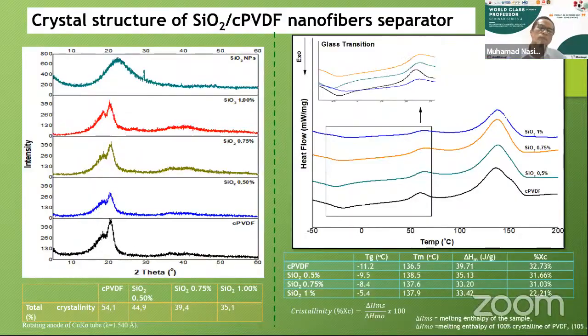And then we confirm by XRD. You can see here this peak is related to beta phase, and this is related to alpha phase. And then we measure the crystallinity. So the crystallinity of pristine co-PVDF is around 54%. By adding the nanosilica, the crystallinity decreased.